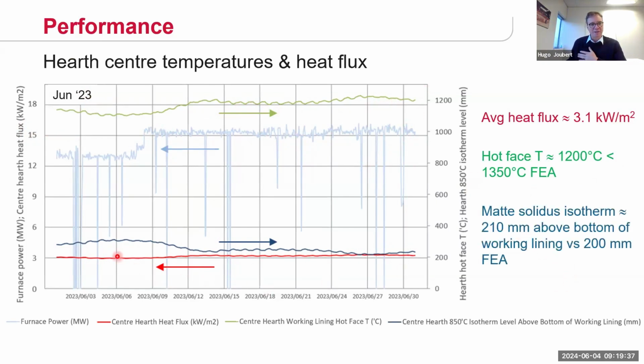And then if you look at the navy blue line here, that is the matte solidus isotherm position above the bottom of the working lining, and we settled about 210 millimeters above it compared to the 200 that we originally estimated.